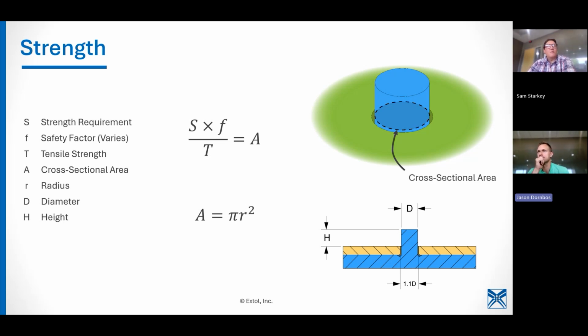With infra, it's a little more static. So with infra, we typically designate a safety factor of about 20%. It does vary because the difference between infra and nano is that the processing temperature can vary your strength drastically. We've seen that the lower temperatures do produce stronger stakes. So it really just depends where you're processing that material and how hot you're processing.